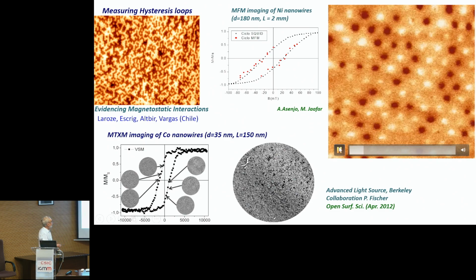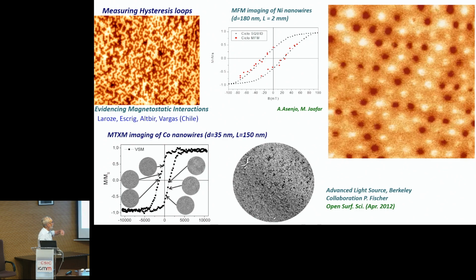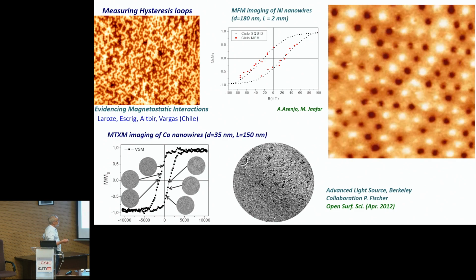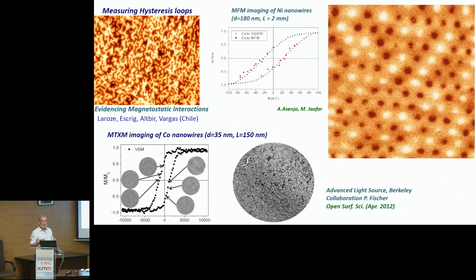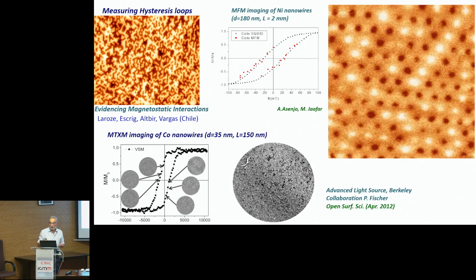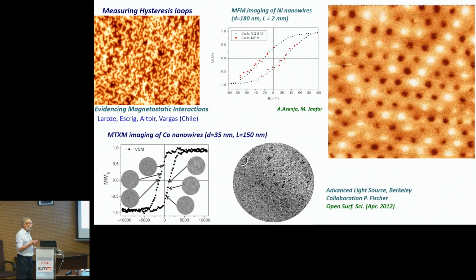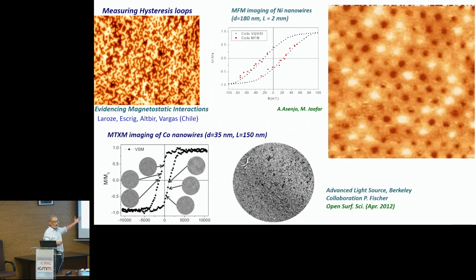As we apply the magnetic field perpendicular to the membrane, you see some black points become white. So they are individually reversing magnetization in each nanowire. So we can observe, even by this magnetic force microscopy technique, the evolution of the global magnetization, but also the individual magnetization of nanowires. And by counting the number of black and white points, we can reproduce the net magnetization, these red points. So they are overlapping with the results with the SQUID.